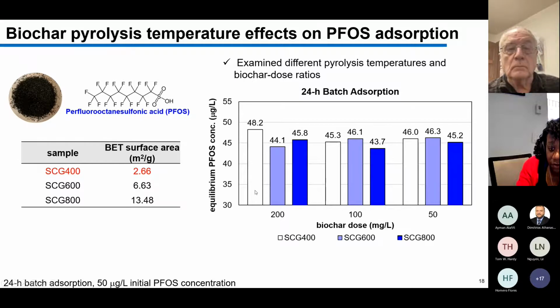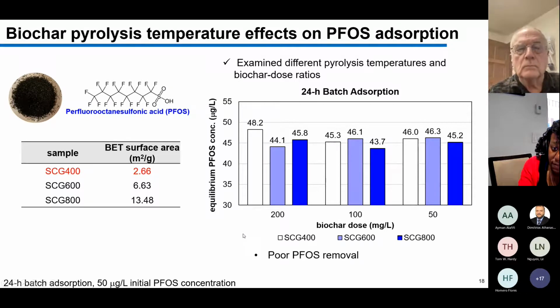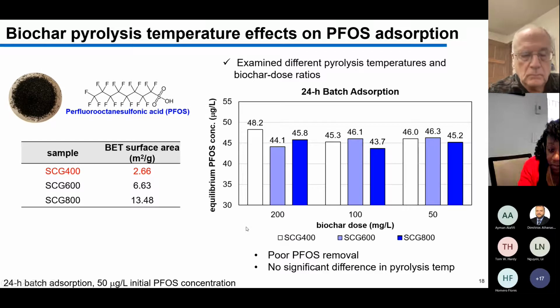And here the different color bars represent the different pyrolysis temperatures. So we started with 50 microgram per liter PFOS in solution, and as you can see here, we're getting very low removal. We're measuring around 50 microgram per liter PFOS in solution. So we have poor PFOS removal. There's no significant difference that we could discern based on the pyrolysis temperature, and we hypothesized it's because we have low surface area, as you can see in this table here.